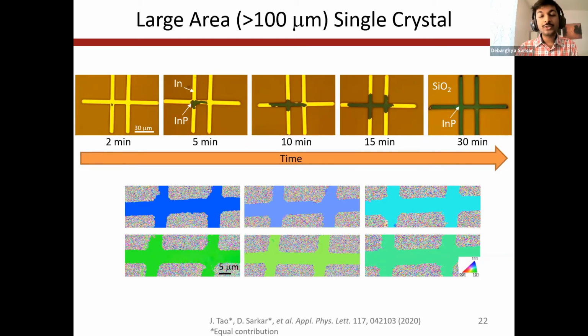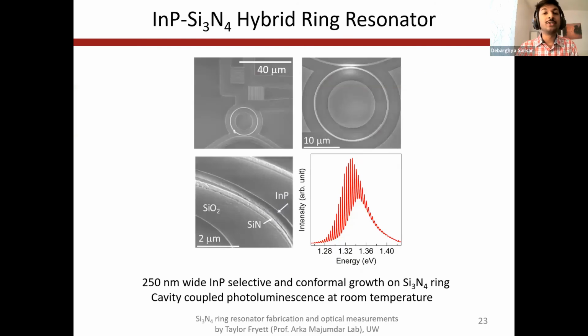We were also able to grow indium phosphide directly on a silicon nitride ring resonator, which are important components for photonic circuits. And this was grown only on top of the silicon nitride and conformally all around the ring. The very good interfacial properties are evidenced by this plot, which shows the photoluminescence from indium phosphide coupled with the cavity resonances given by the spikes of the resonator.